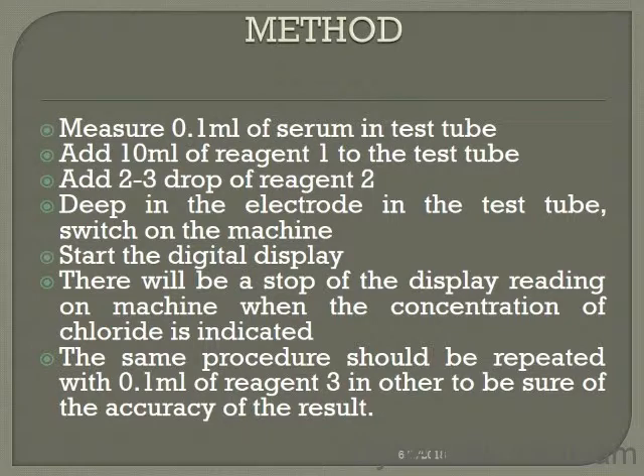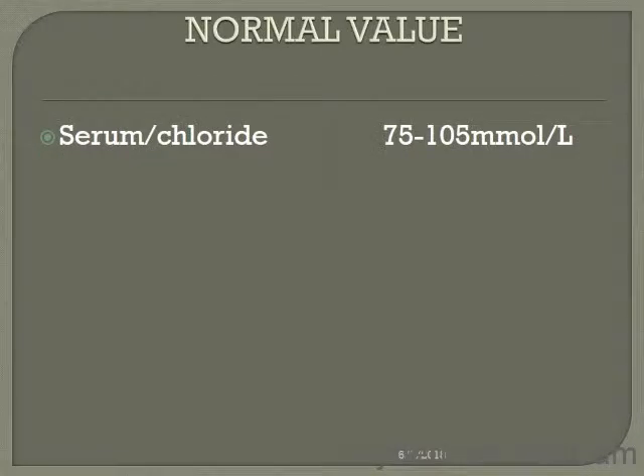Now the method. Measure 0.1 ml of the sample in a test tube. Add 2 to 3 drops of reagent 2. Dip the electrode in the test tube. Switch on the machine and start the digital display. The display reading will stop when the concentration of chloride is indicated. The same procedure should be repeated with 0.1 ml of reagent 3 in order to be sure of the accuracy of the result. The normal value of serum chloride is 75 to 105 millimole per liter.